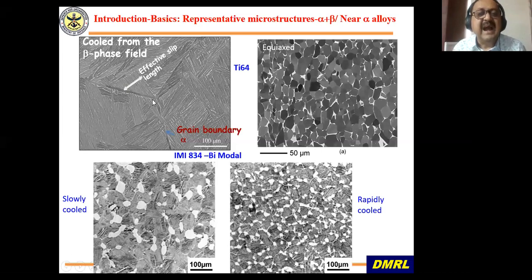start getting affected. And when you beta treat and then cool slowly, in most of the titanium alloys, that is richer titanium alloys, you get what is known as grain boundary alpha. That is, alpha precipitates along the grain boundaries, and there is a region which is denuded of alloying elements, and that is a path where the deformation can proceed easily, and is many a time the cause of many of the failures. So you have to be careful when you are talking about richer alloys, and when you are heat treating, you should try not to get alpha along the boundaries.